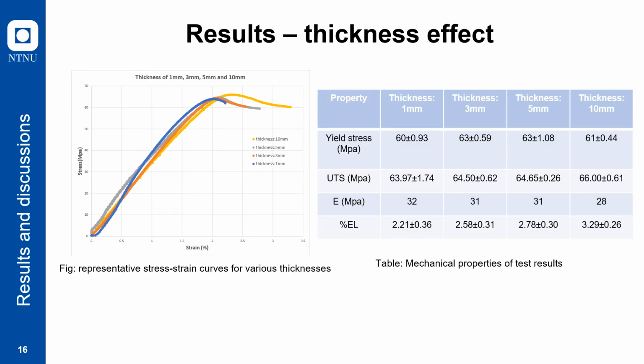So this is the result for all 4 thicknesses, and as you can see from this stress and strain plot and the data we have reported in this table, as thickness increases, the ultimate tensile strength also has a tendency to increase, even though there is not much difference between the 3 mm one and the 5 mm ones. And also the elongation at failure increases when the thickness increases.